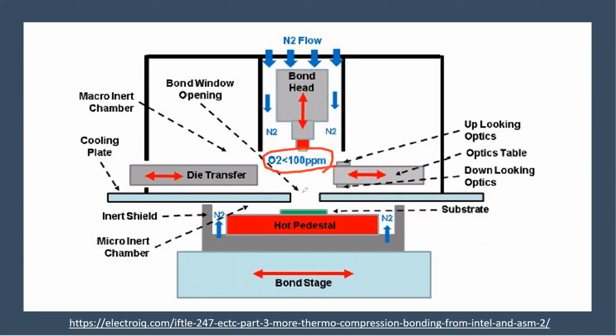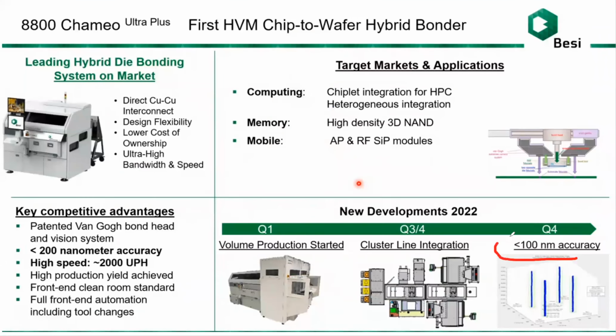You cannot have very high oxygen content because copper will oxidize very easily in air. So you demand that the O2 be less than 100 ppm. So the whole thing has to be in vacuum, right? And you move your robot inside a vacuum. Not a thing that's easy to do. And then at the end of the day, you need to have less than 100 nanometer accuracy. Okay, so that's why it's challenging. Very few companies in the world can do that. EVG and Besi seem to be the big boys.